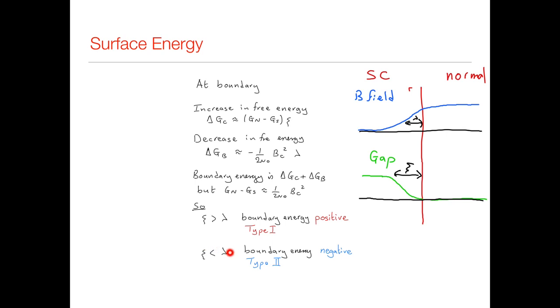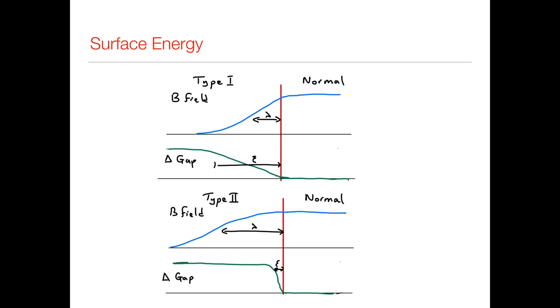But if we're in the other regime, the surface energy is negative. So it can be favorable for the material to have multiple surfaces. And this is indicative of the type 2 behavior, because when we're in the higher field state, we end up with positions where we have alternating superconducting and normal regions. And that's how the magnetic field is going to penetrate the material. So I've drawn this out schematically, showing you how the B field varies and is determined by the penetration depth lambda, and how the gap varies with the coherence length. And we've got the situation of type 1 and the situation of type 2 where they're reversed around.